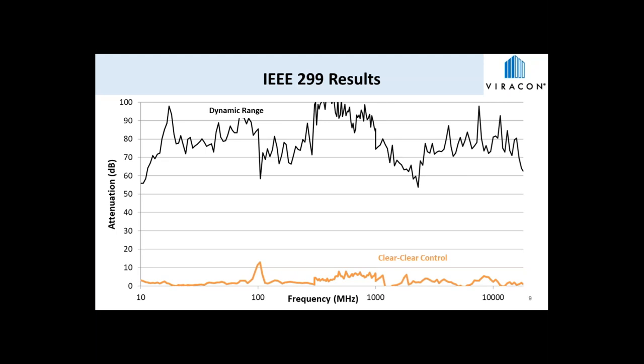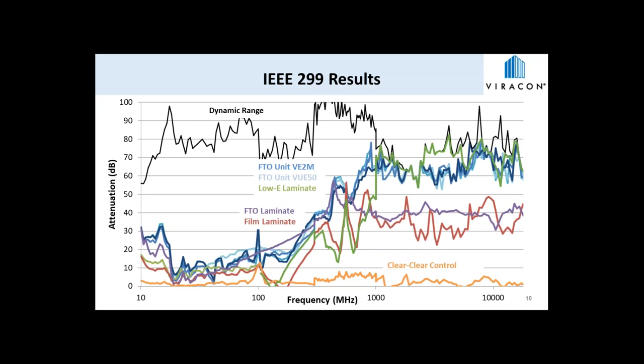So you can see the dynamic range in black up top, and the attenuation for the clear control laminate near the bottom. For the most part, the attenuation is under 10 decibels for the clear control laminate, which means it's letting a very strong signal through the glass. So next we'll include the rest of the samples. As expected, each of the samples have a higher attenuation than the clear control laminate, so they are blocking more of the signal. Focusing on the FTO laminate in purple and the RF film laminate in red, both of these samples have a similar attenuation to one another.